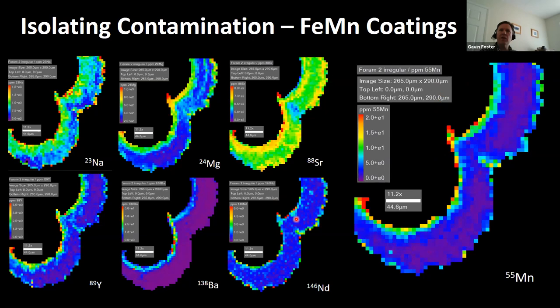Manganese, like I say, as they're falling through the water column, they get coated in a ferromanganese coating. And that ferromanganese coating is enriched in rare earths. In this case, the manganese is very much enriched on the inside of the foram. And similarly, the neodymium is enriched on the inside and on the outside, coincident with the manganese. So most of the neodymium we're measuring in this foram is associated with the manganese coating. The same can be true to a certain extent of yttrium. And then there are questions about how much this magnesium enrichment on the inside of the test is related to the manganese coating, as opposed to actually being in the foram. But if you look, there is a distinction, and the magnesium is high within the early parts, the inner parts of the shell.